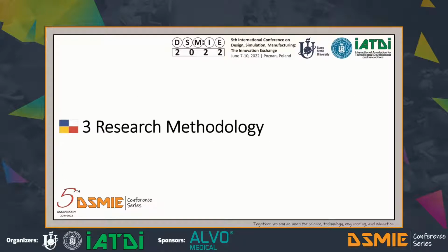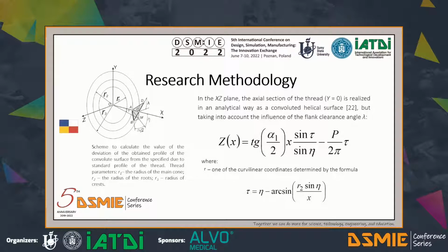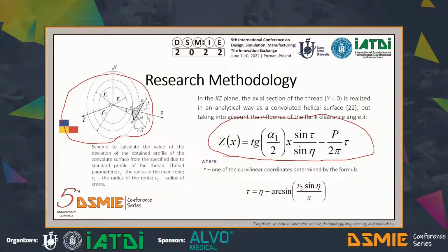Research methodology. Research methodology consists of the next materials. This scheme is to calculate the value of the deviation of the obtained profile of the threaded surface from the specified one due to the standard profile of the thread. This formula was obtained by our researchers before in the XZ plane of the axial section of the thread, where y is 0, and is realized in the analytical way as a convoluted helical surface, but taking into account the influence of the flank clearance angle lambda.